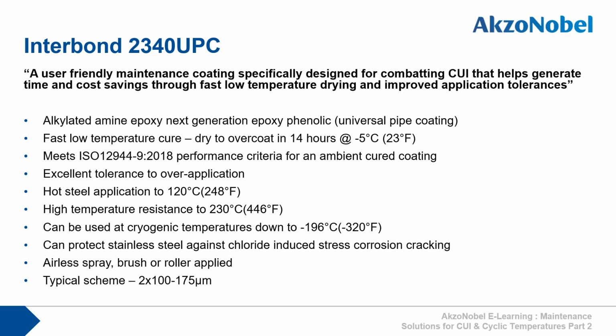2340 UPC has fast, low-temperature cure and is dry to overcoat in 14 hours at -5 degrees Celsius. It meets the ISO 12944 Part 9 performance criteria for an ambient cured coating. It has excellent tolerance to over-application, can be applied to hot steel up to 120 degrees Celsius, has high temperature resistance to 230 degrees Celsius, can be used at cryogenic temperatures down to -196 degrees Celsius, and can protect stainless steel against chloride-induced stress corrosion cracking.